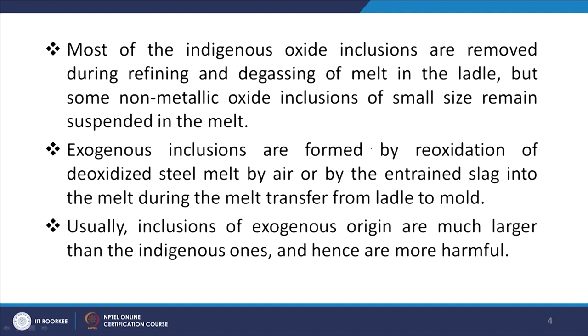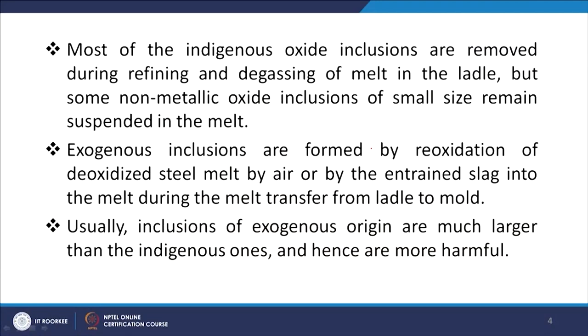However, some non-metallic oxide inclusions of small size still remain suspended in the melt and will carry over into the tundish. The second variety — exogenous inclusions — are formed by the reoxidation of deoxidized steel melt by air or by entrained slag into the melt during transfer from the ladle to the mold.